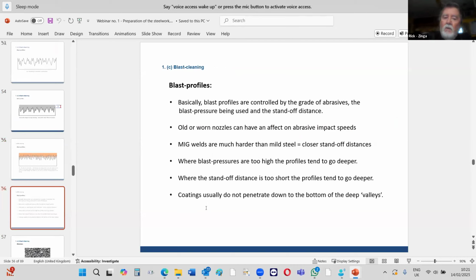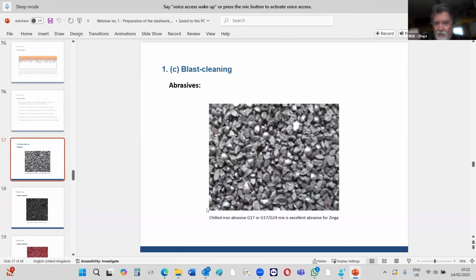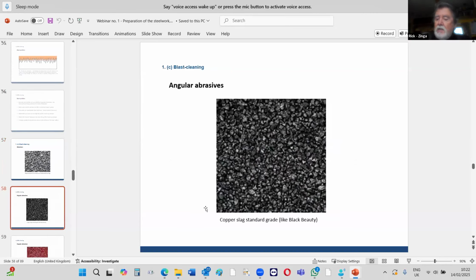And it says here, okay, for MIG welds, when you're blasting MIG welds, you must hold your blast nozzle a bit closer, because those welds are full of manganese, so they're extremely hard. So you have to blast it a bit more slowly, or hold your blast nozzle a bit closer. So this is just to achieve the correct blast profiles. But you can read about this. There's your chilled iron, which to me is number one in the world. Then copper slag, which is used all over the world, in every single country.